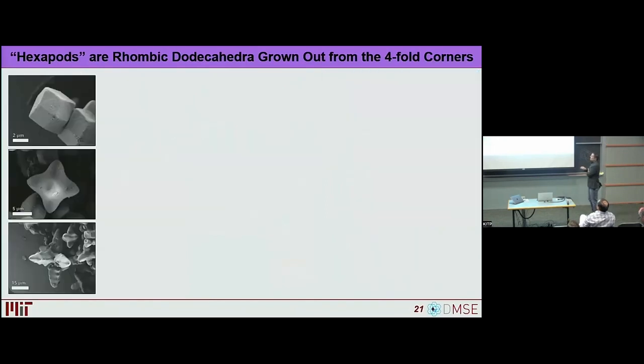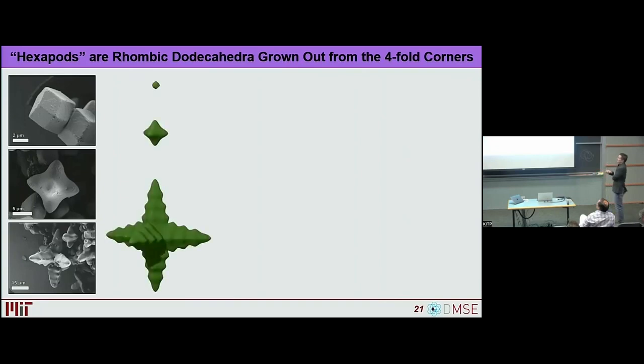Well, if we look at the different types of structures, these are the rhombic dodecahedra and the hexapods and the more stellated type structures. These images are a little bit misleading because it's hard for our eyes to basically look at these scale bars and do the math. So let me show you exactly what these things look like drawn to scale. Sure enough, the smaller ones tend to be rhombic dodecahedra, and we only see the more stellated structures when they get significantly larger. So mechanistically, we're still trying to be a little bit more specific in exactly what's going on here, but what we think is going on is basically coming down to two different underlying principles.